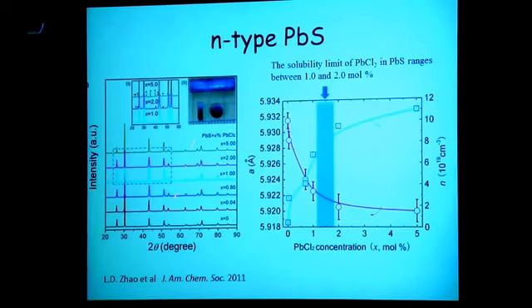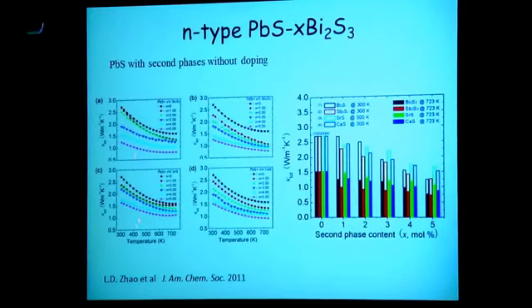These are the samples. You can make the samples. First, we had to look at the pure material just to reproduce what the Russians did. So this is pure, non-nanostructuring. We can add lead chloride, and we can raise the carrier concentration here in this line here. This line here is carrier concentrations. Lattice goes down because chloride is smaller. So everything behaves well. You can dope this. It's clean. And we did all the measurements here. I'm not going to show you that data. We did find that the Russians were right. And then we went to this system with bismuth sulfide.